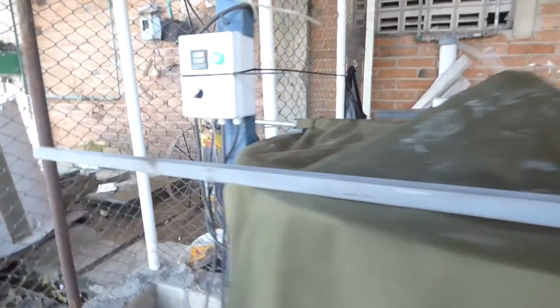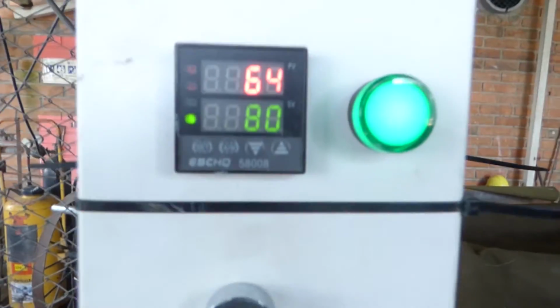So post curing in this case is going to be done with this electrical resistance. We are going to do the post curing process for 6 hours at 80 Celsius degrees. That's it. With that temperature and that time, you're going to have a really strong piece.